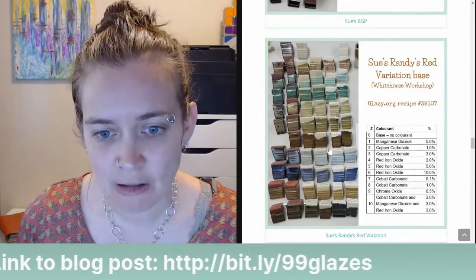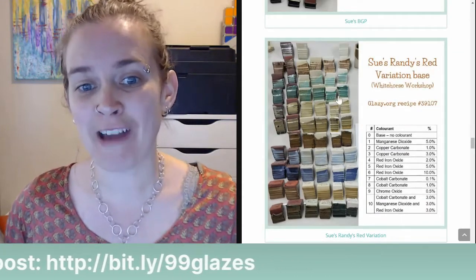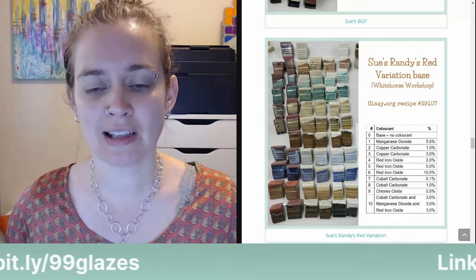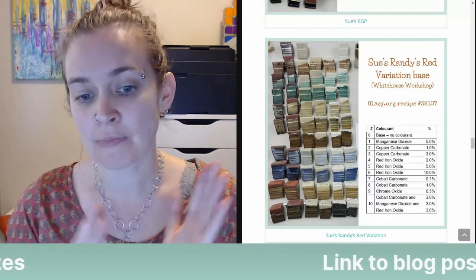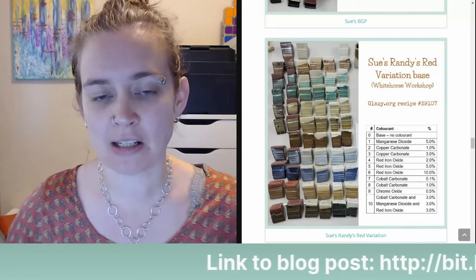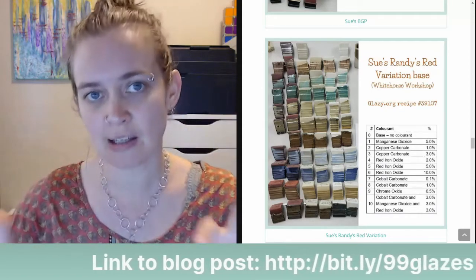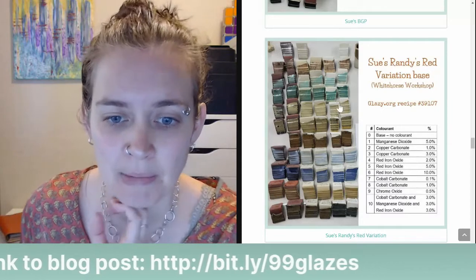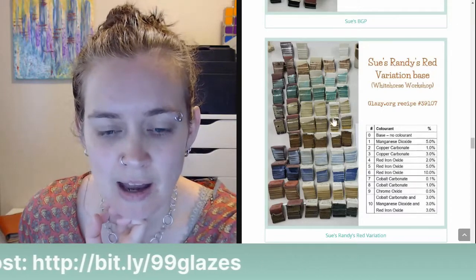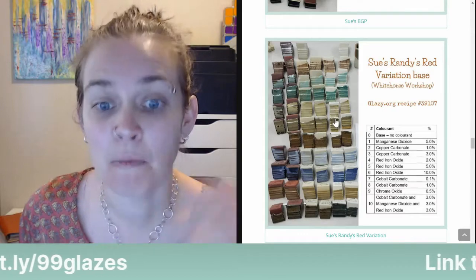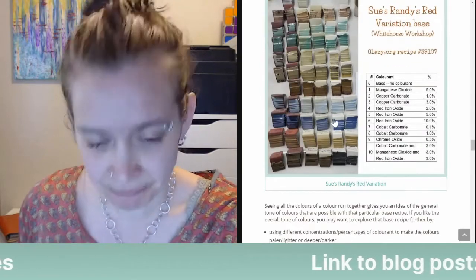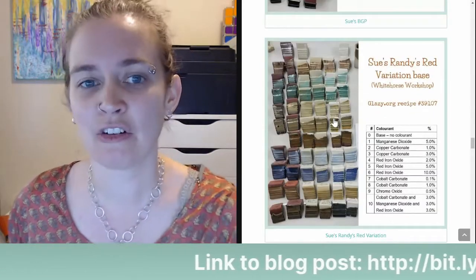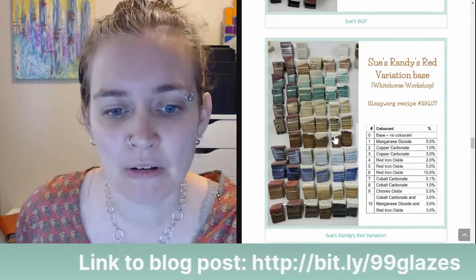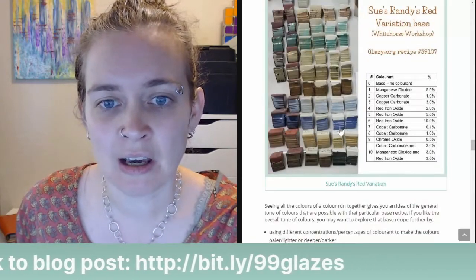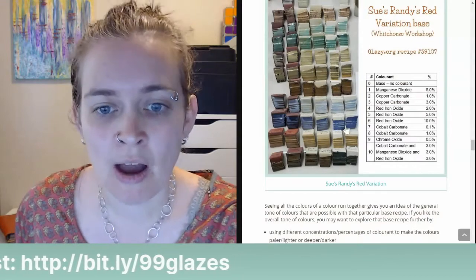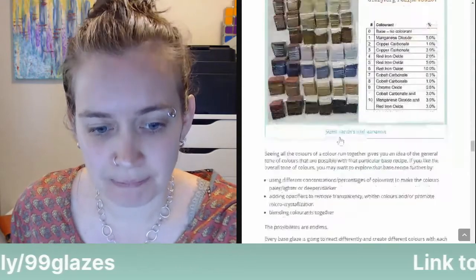Some really nice crystallization happening. This glaze ran a lot. So if you're going to try this glaze and you're firing to cone 6, just make sure you're protecting your kiln shelves, or you're only using it near the top, or you're using a thin application, because this base glaze, a lot of the samples ran. But our kiln also slightly overfired in some parts of the kiln. We had some cone 7s going down around the kiln. So that could be a factor as well.